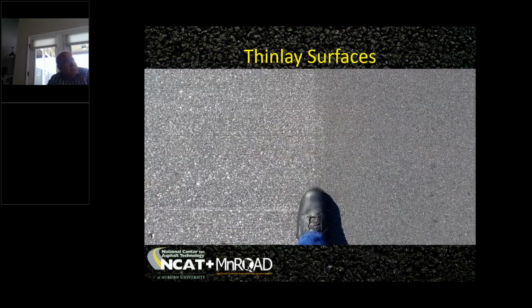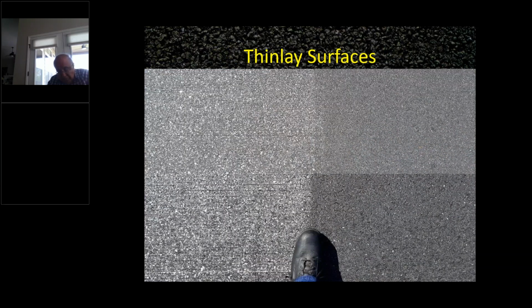But then in 2 other sections, we came back and said, okay, well, let's put thin lays on top of that full depth rapid rebuild and see how much smoothness correction we can make. So on the top of this slide is a 4.75 millimeter nominal maximum aggregate size dense graded mix that was placed a 1/2 inch thick. And then the one on the bottom that you see there is a 4.75 SMA that was placed 3/4 of an inch thick. And in both of those cases, we were able to bridge over the roughness issues associated with that thick placement. And then the roughness is not reflected in these surface mixes. Now they've been down for 7 million ESALs, and performance is really good.